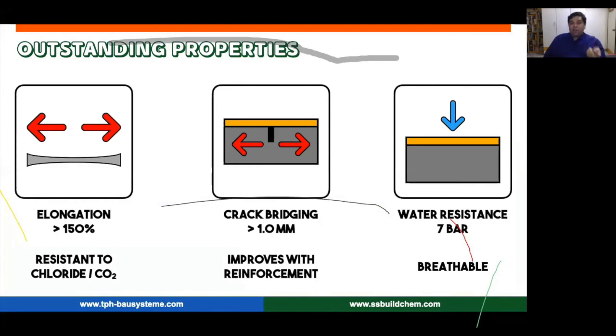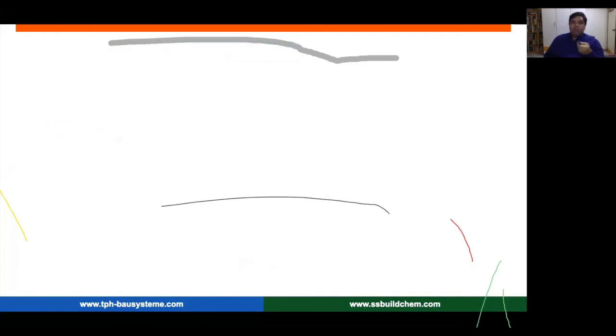The outstanding properties that we talk about for this particular material is that it has an elongation of over 150%. That means it's very flexible. It's almost as flexible or a bit more than the initial picture that you saw. It's got very good crack bridging properties, almost about a millimeter, and is resistant to water pressure of 7 bar. This material is highly polymer modified, so it's resistant to chlorides and carbon dioxide. The crack bridging ability or the tensile strength also improves drastically with reinforcement. You can use a simple AR glass fiber mesh or a fleece, and it really helps to improve the properties. And of course, last but not least, the material is breathable.